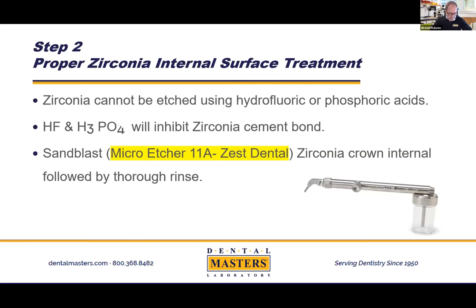Step number two, proper zirconia internal surface treatment. As Dr. Cascone pointed out, zirconia cannot be etched using hydrofluoric or phosphoric acid. Actually, the use of phosphoric is only going to create a problem. Both of these will inhibit the zirconia cement bond. They're literally going to act to seal off the surface and render it inert. So what do we want to do? We want to sandblast the internal surface, followed by a thorough rinse.